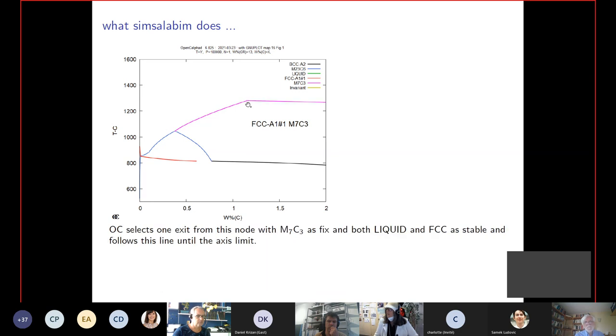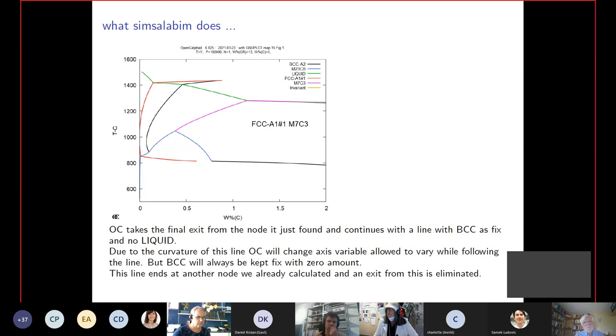It will follow the FCC disappearing in this region, and then it has finished all the points here, but it has another node point which it hasn't used yet, so it will continue here where the M7 carbide is no longer stable. So on this side we have just FCC, on this side we have FCC and M7, and here it stops because liquid becomes stable. And then it calculates a line where the M7 carbide is again zero, and then it will gather another line where the liquid has zero amount, and then it goes on like this, following the different lines where you have a zero amount of one of the phases. And here we again find this invariant equilibrium, and we have some more lines in equilibrium with the liquid.